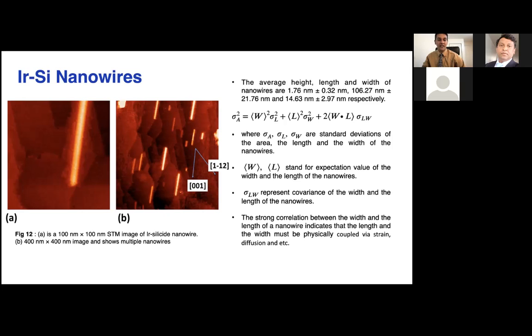Before we studied any physical or chemical properties, we did something very basic. We did dimension analysis. So we measured the length and width: the average length of a nanowire is around 100 nanometers, the average width around 22 nanometers, and the average height around 1.7 nanometers.